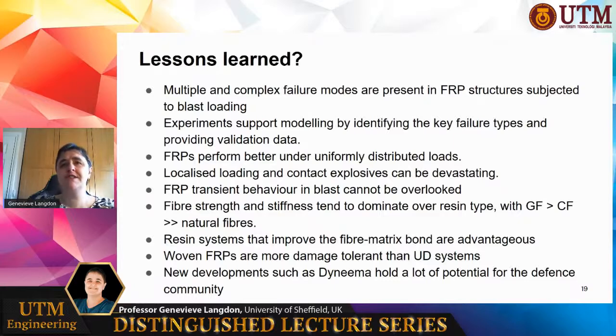The transient response is really important in a material, particularly with a lot of elasticity, such as an FRP. Fiber strength and stiffness tend to dominate over the resin properties, with glass fiber being better than carbon fiber, and those are better than natural fibers. But resin systems can improve the fiber matrix bond, and so those can be advantageous. Woven fibers tend to be more damage tolerant than unidirectional systems. And there's a lot of potential to optimize stacking and weave geometry. And new developments such as Dyneema hold a lot of potential for the defense community.